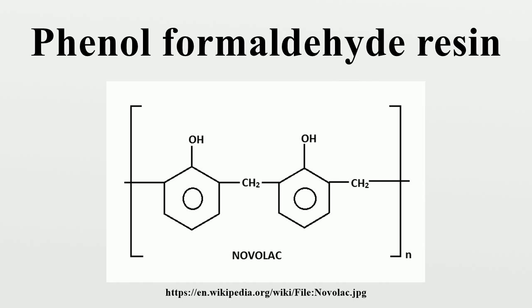Hexamethylenetetramine, or hexamine, is a hardener added to cross-link novolacs. At a temperature greater than 90 degrees Celsius, it forms methylene and dimethylene amino bridges.